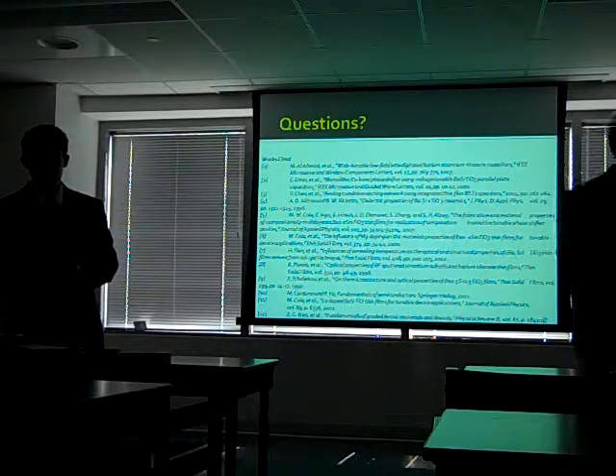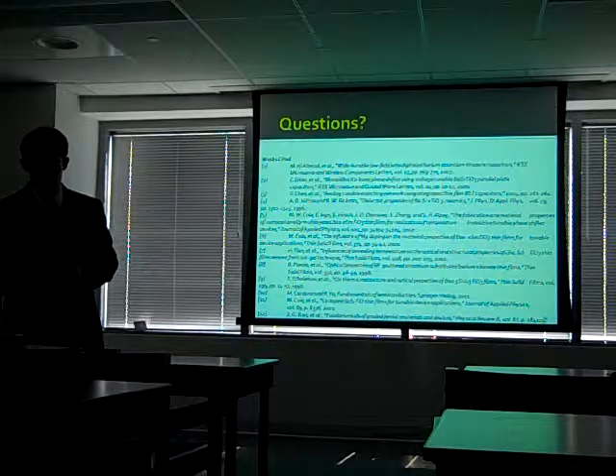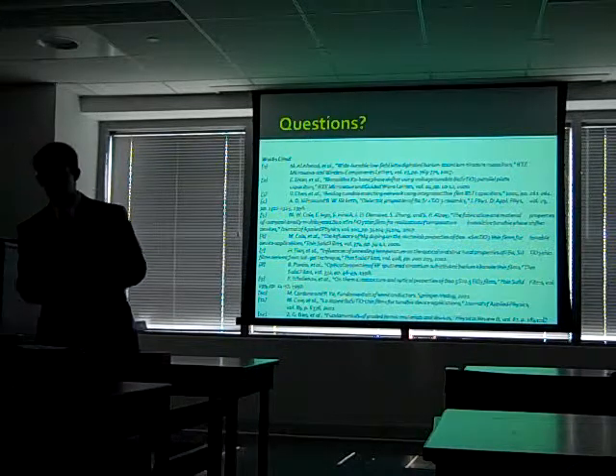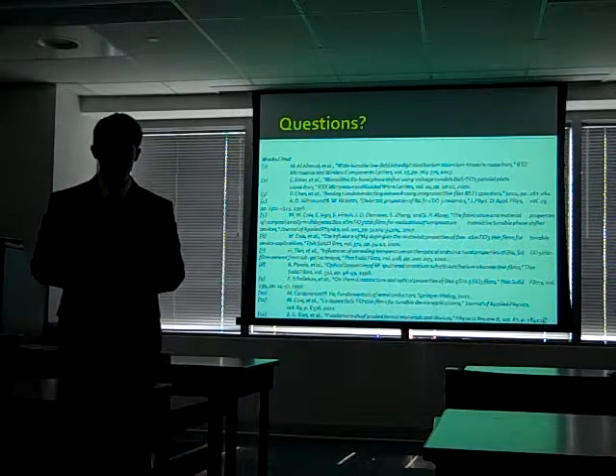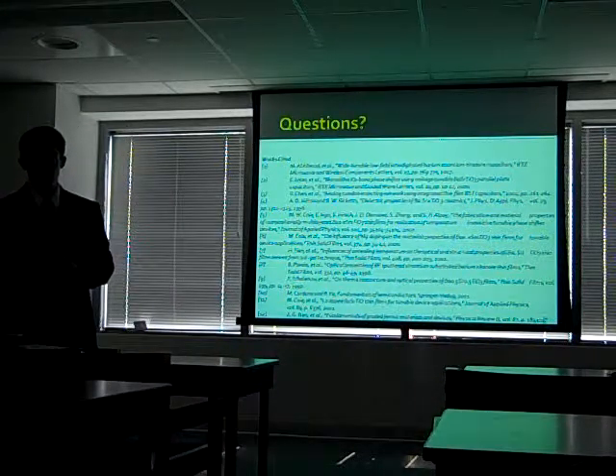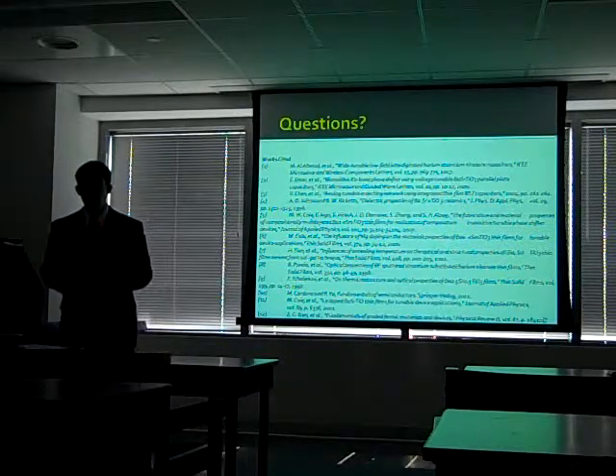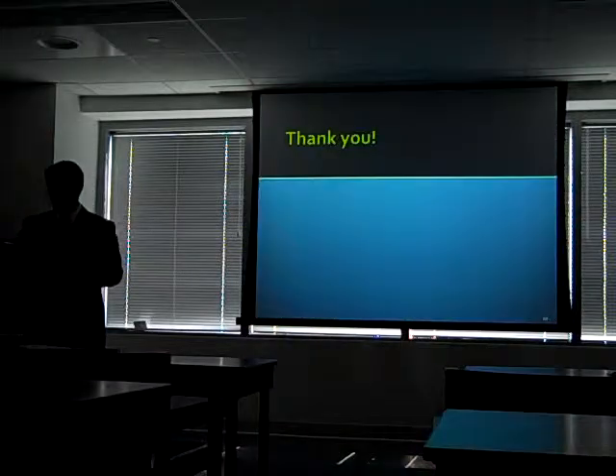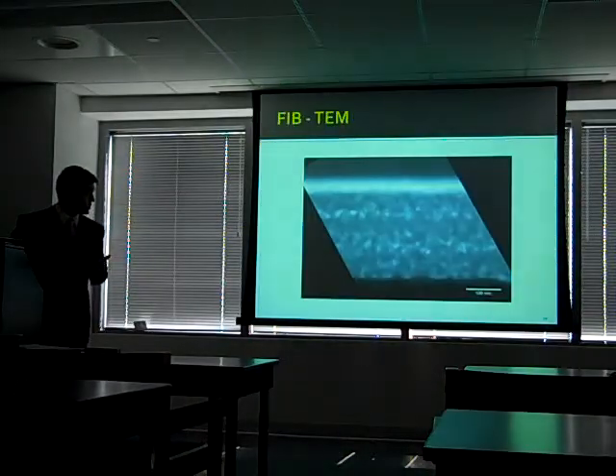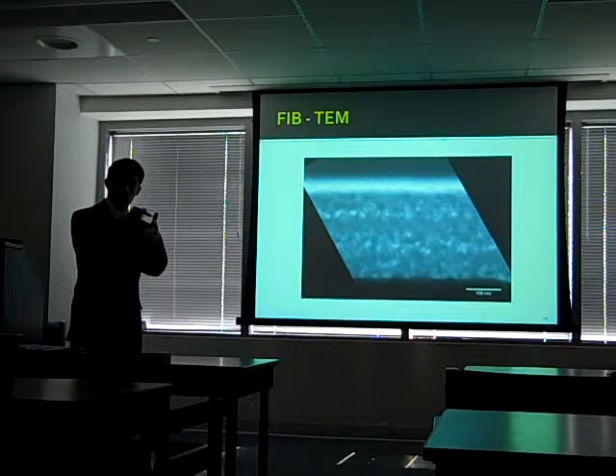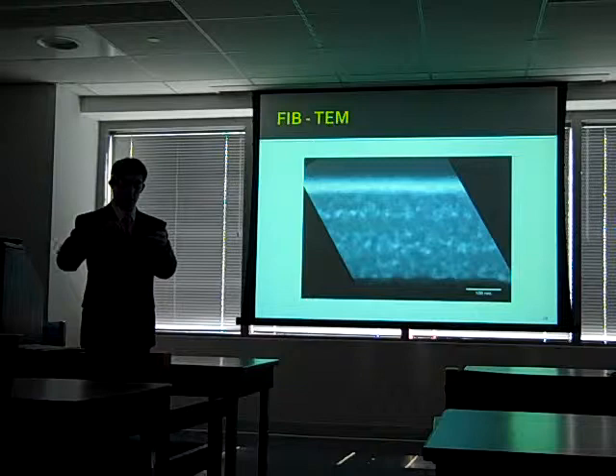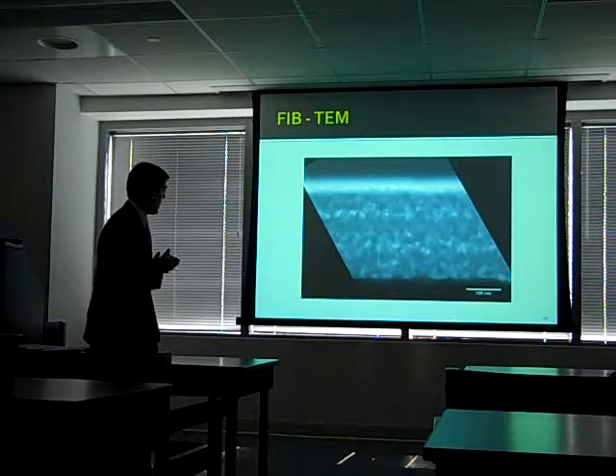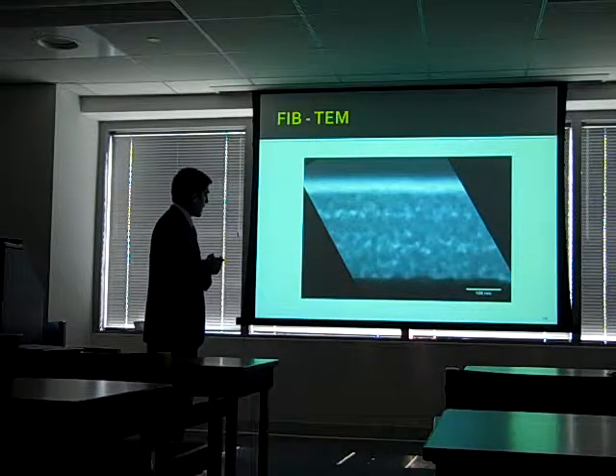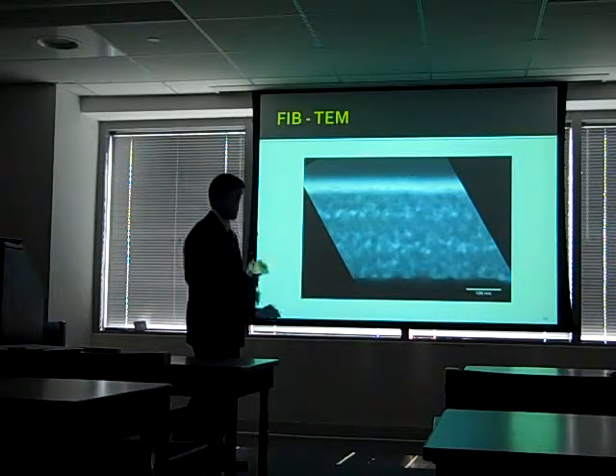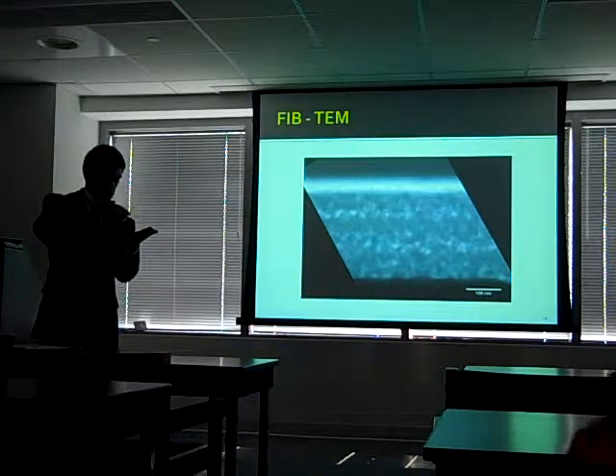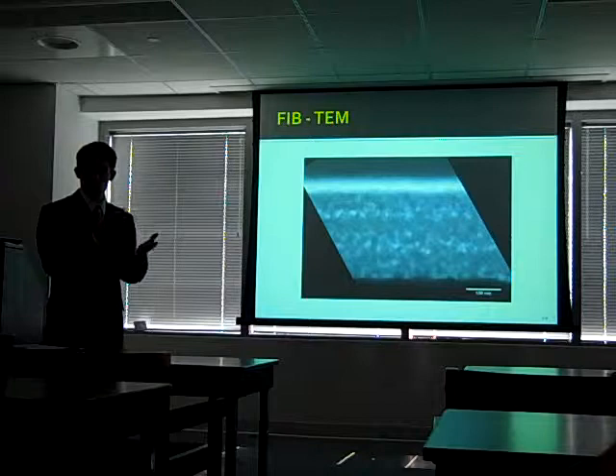When you had those graded layers, one of the layers had 33% porosity. How did you determine that there was porosity in those layers? Because you said you did spin coating, so I would assume that the top layer went into the roughness of the previous layer, so it would have been 67% top layer, rather than having that 1/3 porosity. The reason that I came to that conclusion was that TEM is a tunneling technique, and so light areas correspond to areas where a lot of electrons are able to get through. So I attributed that to voids in there. You're right, with the MOSD technique, you would expect it to wet the surface, however rough it is.